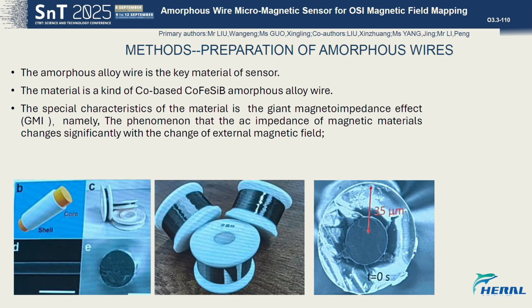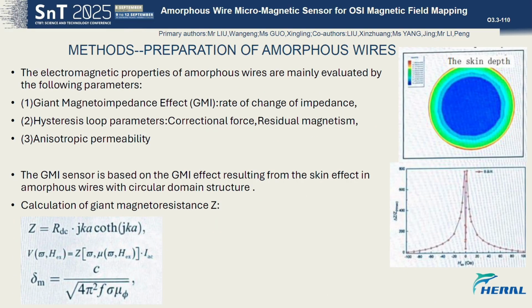The special characteristic of the material is the giant magnetoimpedance effect, namely the phenomenon that the AC impedance of magnetic materials changes significantly with the change of external magnetic field. The electromagnetic properties of amorphous wires are mainly evaluated by the following parameters. The first is the giant magnetoimpedance effect, such as rate of change of impedance. The second, hysteresis loop parameters, such as coercive force and residual magnetism. The third is anisotropic permeability.